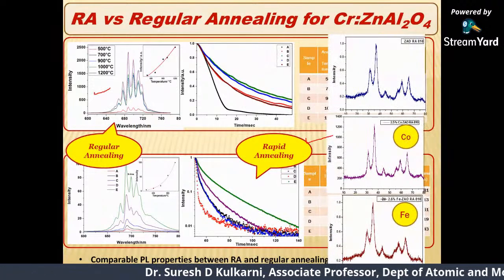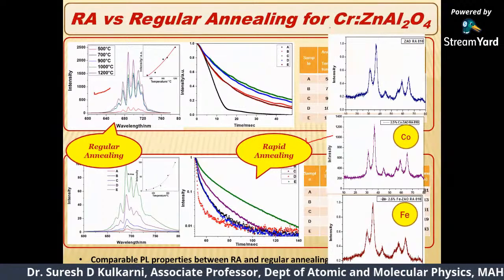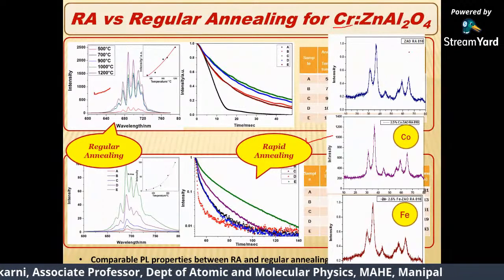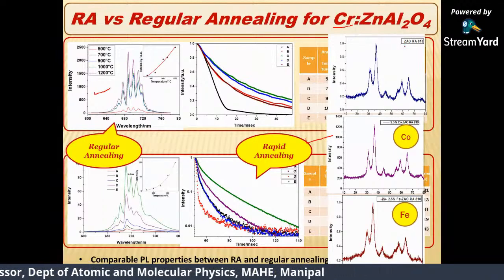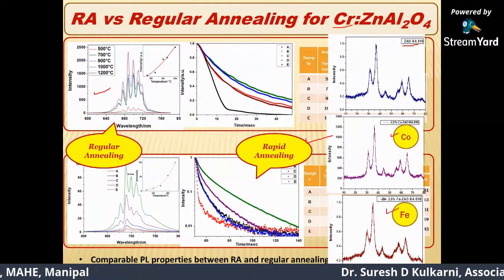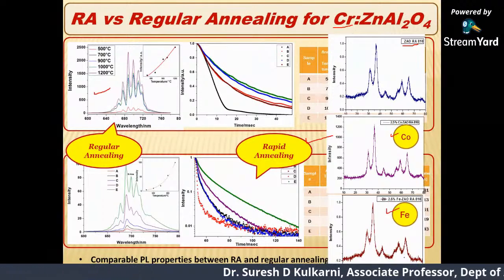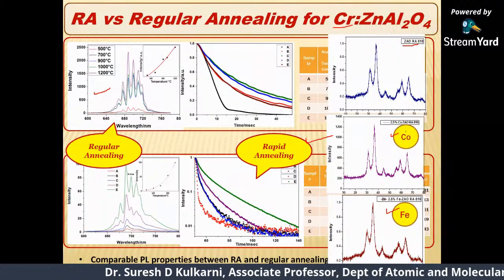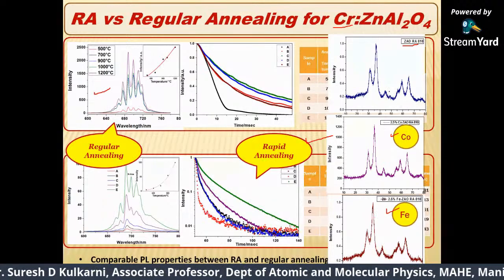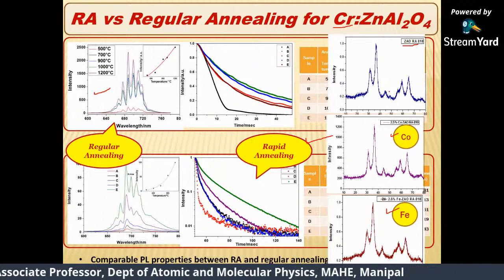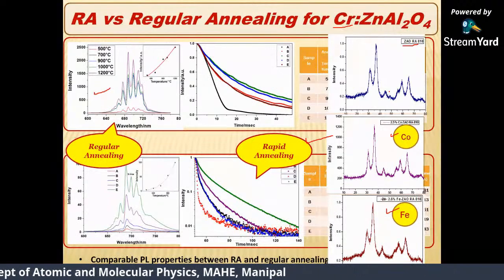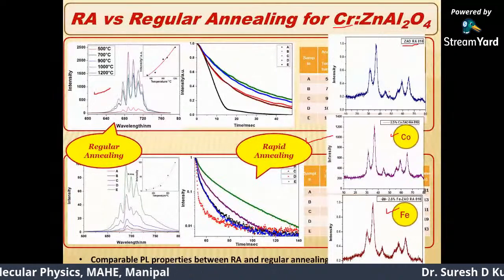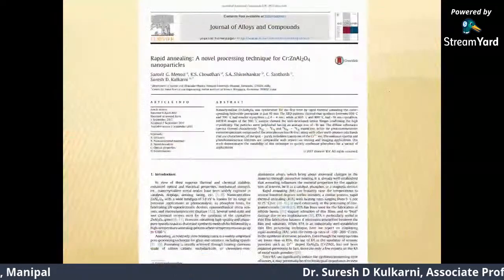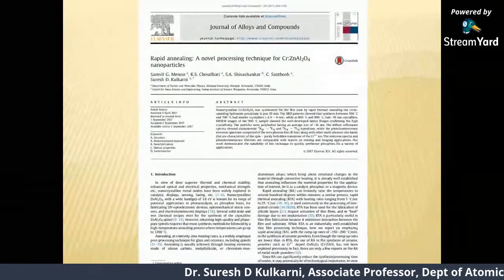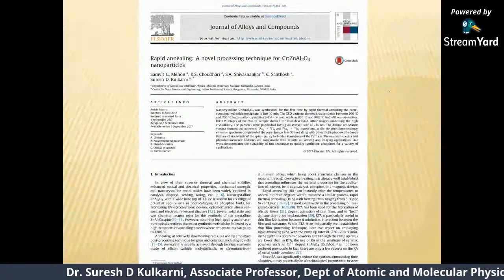And later the question may come, okay, whether it works only for chromium containing materials. We have done it on different materials: an undoped zinc aluminate, where there is no dopant. We have put cobalt as a dopant, we have put iron as a dopant, and a variety of other materials. And you can see these are the XRD patterns showing crystalline materials are formed within minutes. From start to end, in about 30 to 40 minutes, I synthesize as well as finish the processing of these materials. It's an important thing, so we published it in the Journal of Alloys and Compounds. Details can be found there.